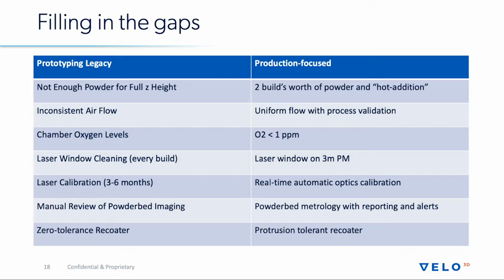We have hot addition of powder, so you can add powder live during the build. The gas flow uniformity is actually validated through the process metrology, not just through CFD. So we know that the process outcomes are consistent based on that metrology. Oxygen level and humidity monitoring comes standard in the system. You saw it reported out on the build GUI. This is part of the build report that you get at the end of a build from our database.